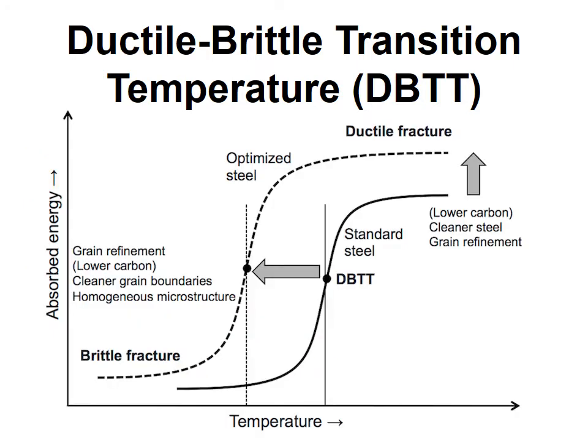In this slide, a typical DBTT graph is shown. With reference to the diagram, both graphs are identical in that as temperature drops, the amount of impact energy the metal can withstand also begins to gradually reduce, but is still ductile to a point where a drastic transition to the brittle state takes place. Comparing the optimized steel to that of the normal steel, it can be seen that the standard steel starts to dip at a higher temperature as compared to the optimized steel, and therefore it will become brittle earlier and lose its ability to absorb shock should the temperature begin to drop.